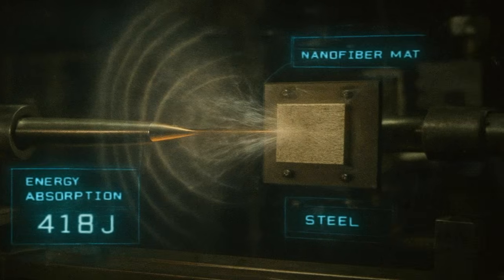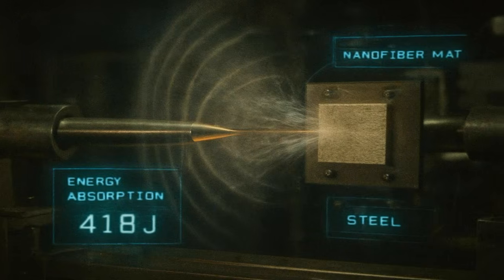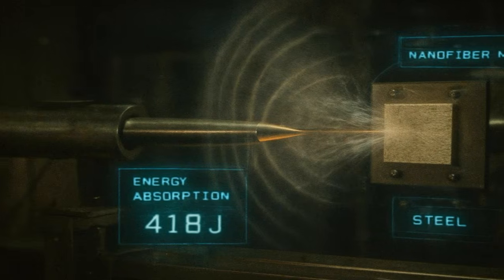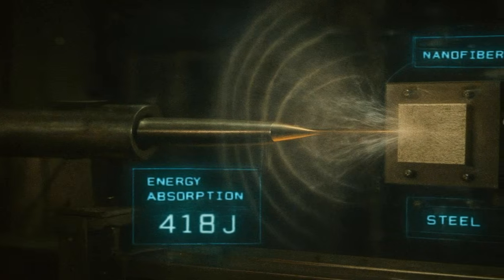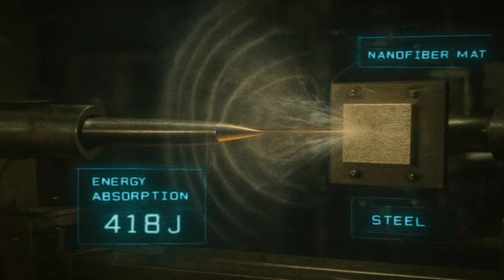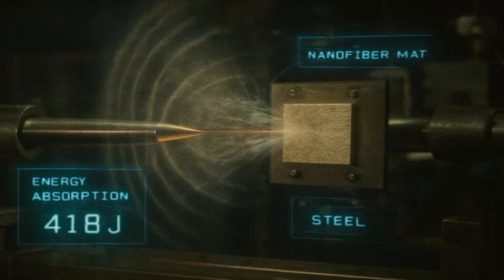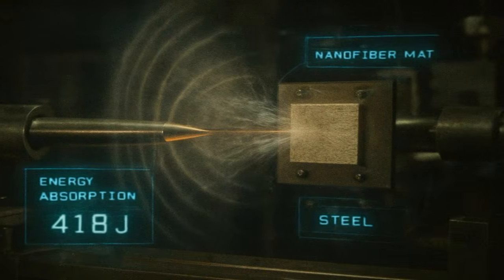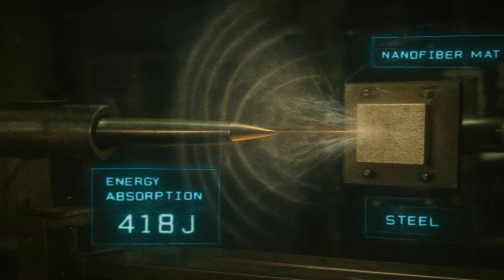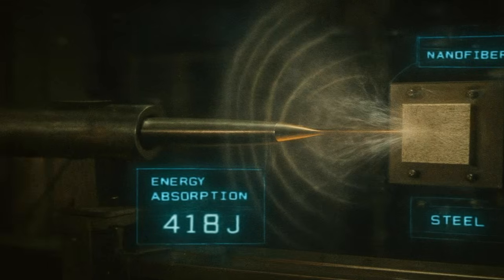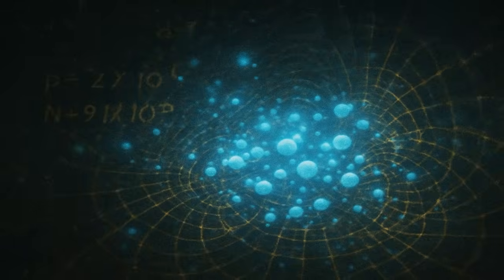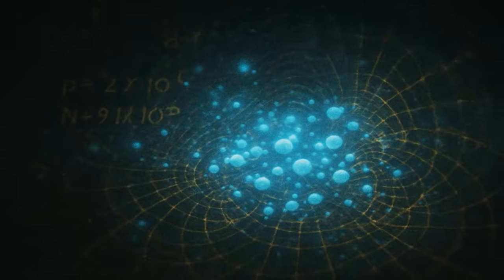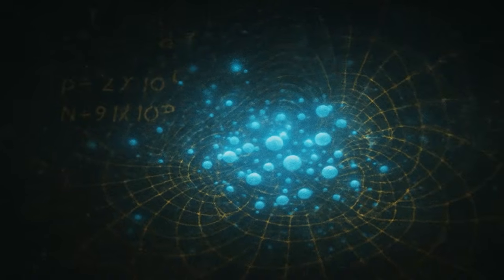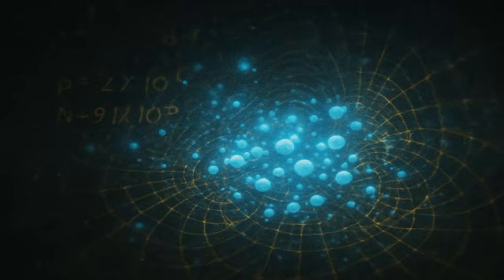When steel is deformed very rapidly, there's no time for heat to dissipate. The energy from plastic deformation converts to heat locally. The temperature rises. The hot region becomes softer, easier to deform. More deformation concentrates in that region. The temperature rises further. This creates a positive feedback loop. A narrow band of highly deformed hot material forms. This is an adiabatic shear band. It's a localized failure mode that can occur in armor steel when a bullet impacts.